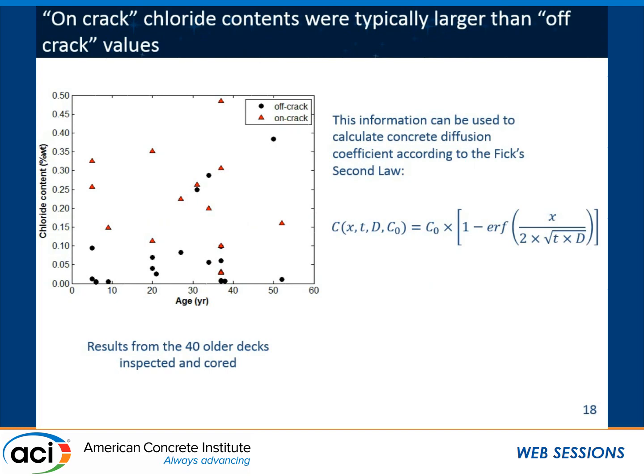Of course, at later ages you can have other issues, like fatigue or structural or mechanical related cracking. We didn't look at crack density against age, but we did look at chloride content and whether the incidence of cracking had an impact on the chloride level. Thank you. Sure.